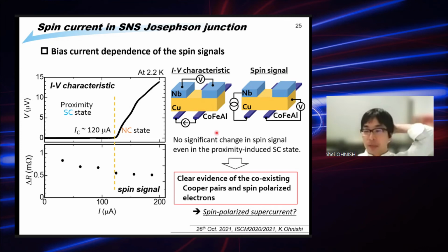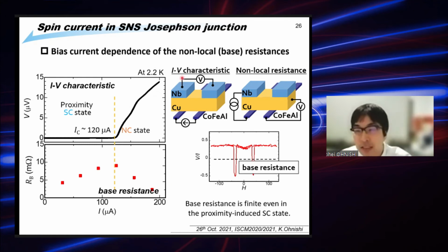In the final part, I'd like to mention whether this is a spin polarized supercurrent or not. The answer is, unfortunately, no. We also plot the base resistance of the non-local resistance. The base resistance is defined by the average of the polarized states and anti-polarized states. In this structure, this base resistance showed some finite value even in the superconducting state, the proximity superconducting state. That means some normal current also flows from the left-hand side to the right-hand side.